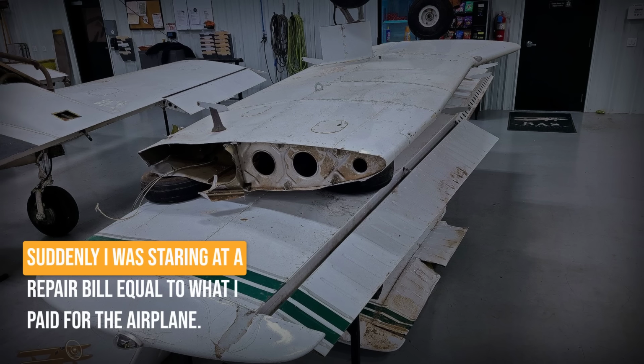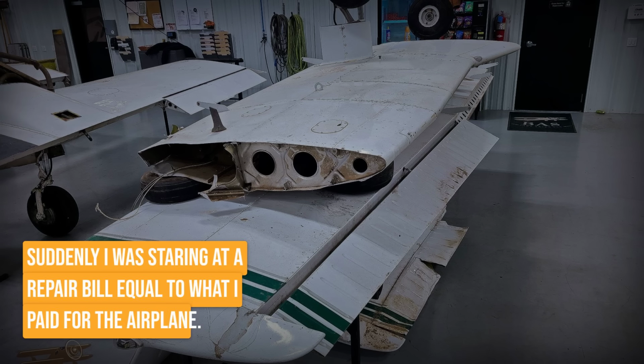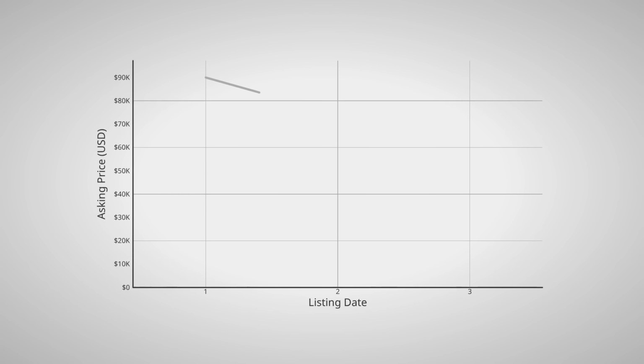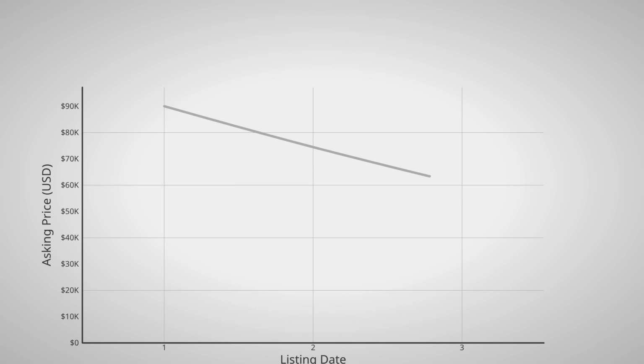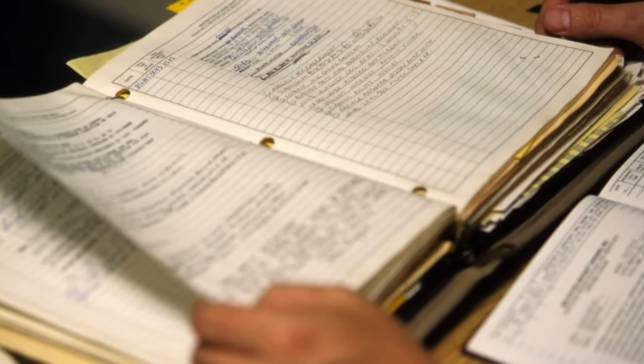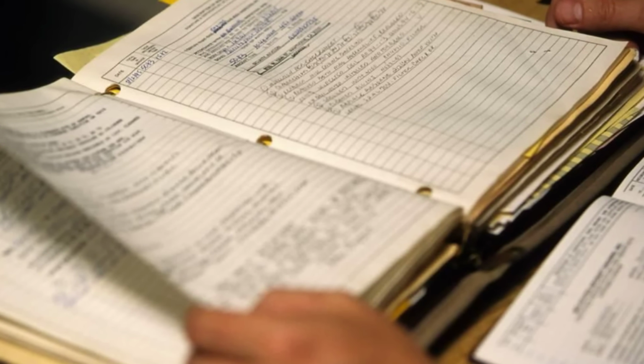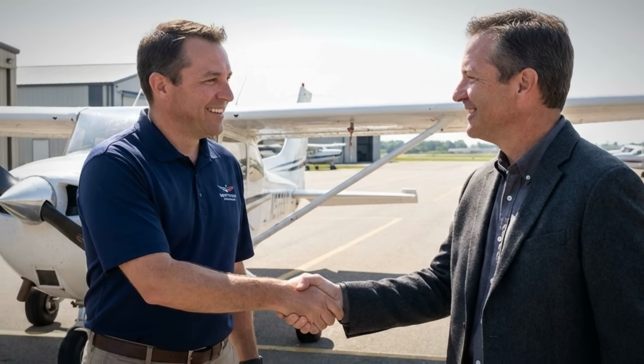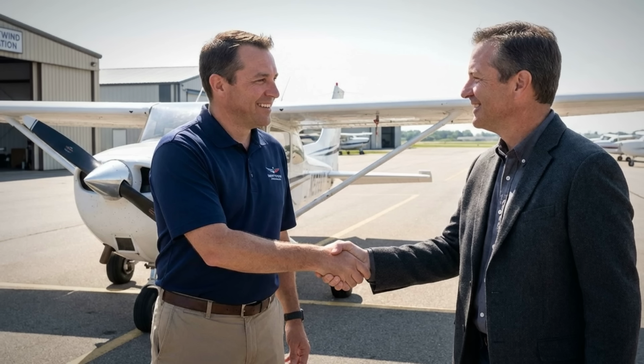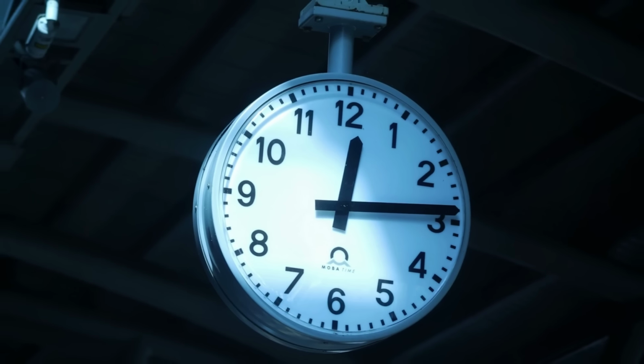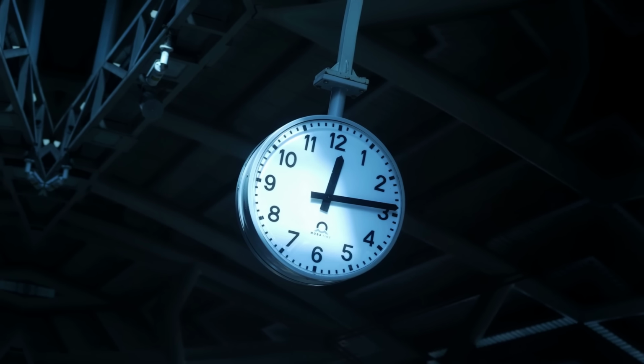Then the inspection found a crack, and suddenly I was looking at a repair bill that matched what I paid for the airplane." The financial hit does not stop at the repair shop. Listings for high-hour, unmodified Cherokees have dropped by $10,000 to $20,000 overnight as buyers factor in the likelihood of a looming spar job. Sellers are forced to negotiate, and buyers who do not ask the right questions risk inheriting a five-figure liability.